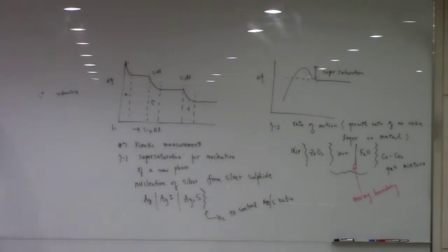Okay, so if you measure the voltage in that case, you're going to have some FeO in a solid solubility limit. We're going to have a supersaturation, and here the plateau is the Fe and FeO two-phase region. Okay?